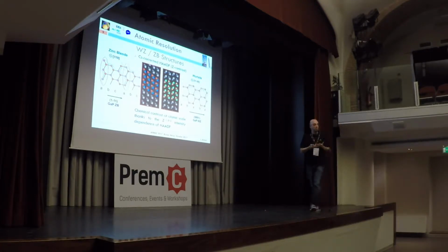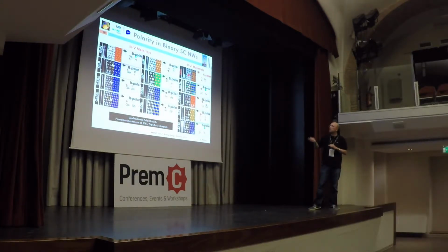So these materials are polar, because you have an electrical field produced inside the material. This gives rise to many properties in these materials. For example, in gallium nitride and in zinc oxide, you have piezoelectricity. You have many different defects at the quantum scale that can be applied here. But it's important to see how these materials are composed. We've been analyzing many of these different materials, all the 3-5 compounds in nanowires, for example, all of these 2-6 compounds. And what we have seen is that in many of the growth conditions in which these materials grow, most of the time they grow with a single polarity.